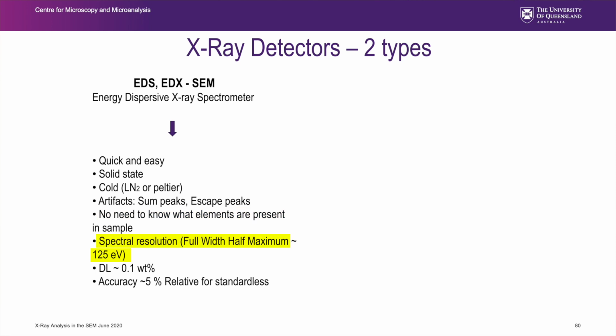Its spectral resolution, full width half maximum, is about 125 eV, but the detection limit is somewhere about 0.1 weight%. And for standardless quant, I'd say its accuracy is roughly 5% relative. We've already talked about that. Sometimes I can get down to 2%, and other times I'm hundreds of percent off.